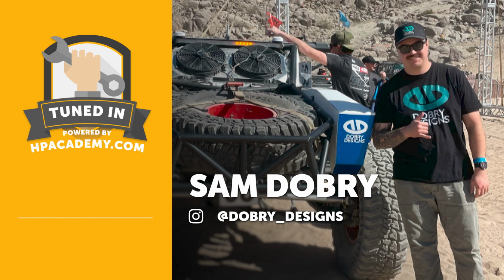So the definite solution, first off, is high quality welds. No undercut is one of the big ones. Proper penetration I shouldn't even have to mention; that's of course standard. And really trying to minimize heat input is a huge one. What I always advise my customers and what I personally practice is pulse TIG welding. You can set up your machine so that instead of just being a constant arc, it pulses, and so you're essentially getting the same amount of penetration without the total amount of induced heat into your system.